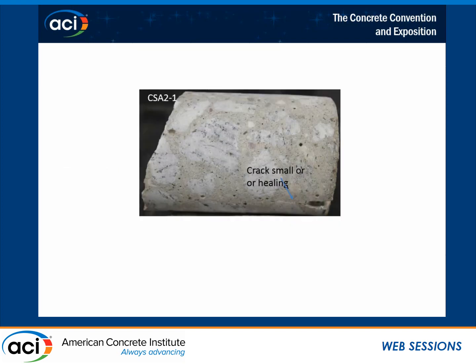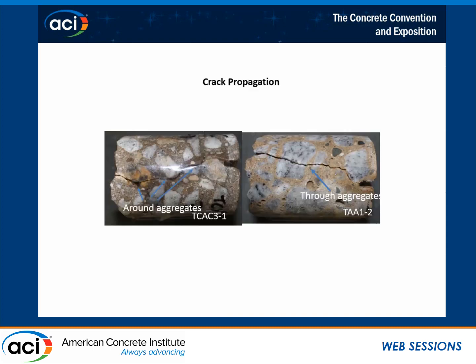Looking at, I believe, another calcium sulfoaluminate sample, you can see in this case the crack was relatively small, so it might have done a little bit of healing. You can see some white stuff over there, so it looks like that crack might have healed again. But I'll show you it didn't have much of an effect on what the chloride was coming in there. Then looking at another type of cement, this is calcium aluminate cement. This cement here showed cracking around the aggregates.